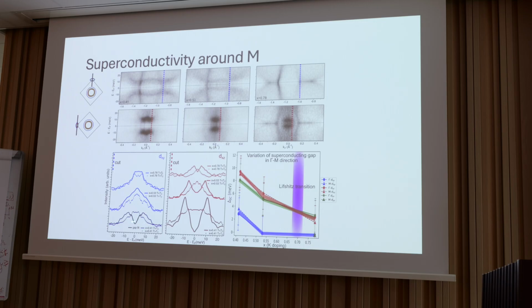But we actually see that the XY pocket around M mirrors what we saw around gamma, where the gap disappears by 53% and stays closed for 78%, whereas the XZ pocket stays open for all these doping levels. And again, this 78% doping is where we don't necessarily expect this pocket to be, but we do see a gap open on this band and close above TC.